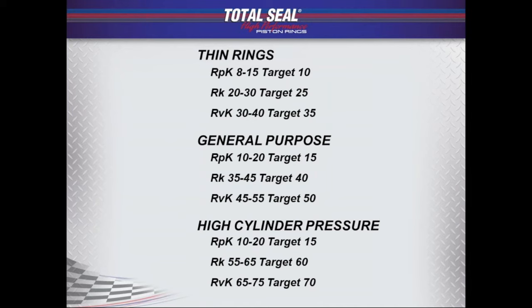Now we can come in and start plateauing with whatever tool we're going to use, a fine grit abrasive, a ball hone, brushes, and we can start going at it slowly. Come in, lighten the pressure up, 4 or 5 strokes, check it. We're not there yet on the peak and the core value, a couple more strokes, check it. Work your way along the line, but keep checking it. Don't wait till you're finished to check the numbers. You may have gone too far, and it's almost always a matter of losing that valley number.